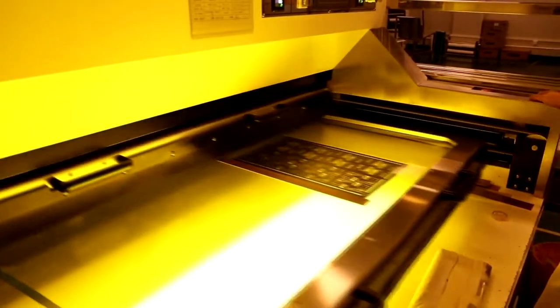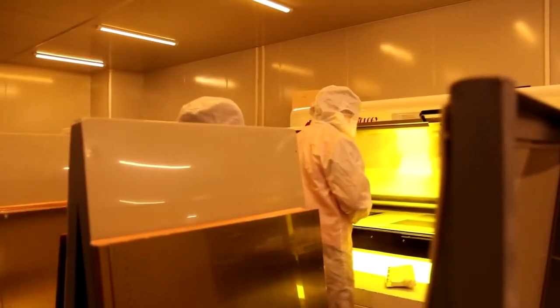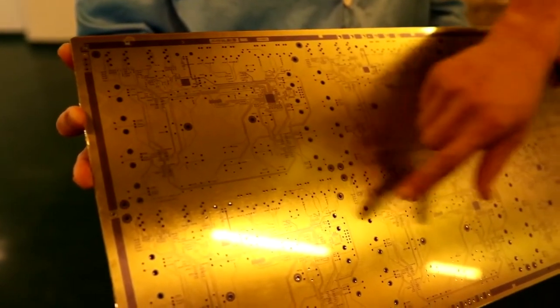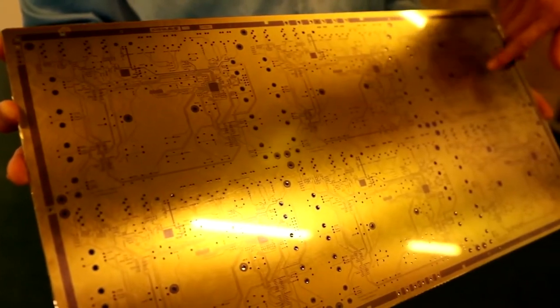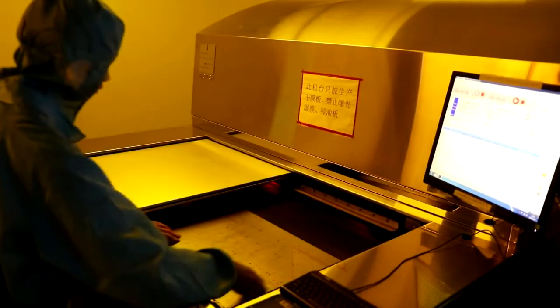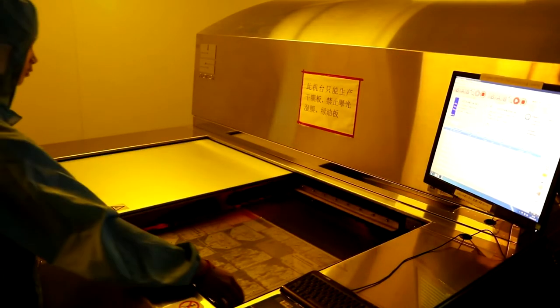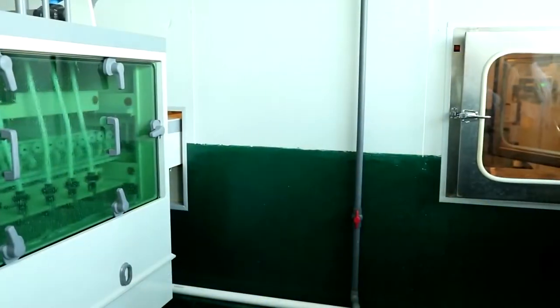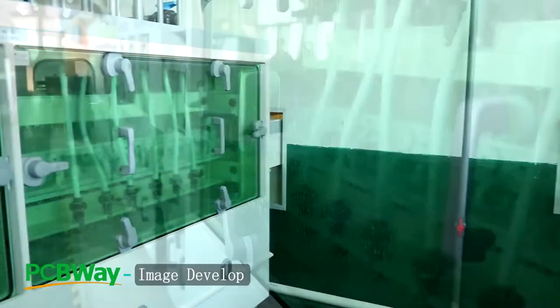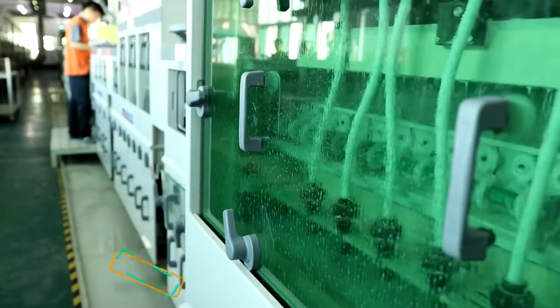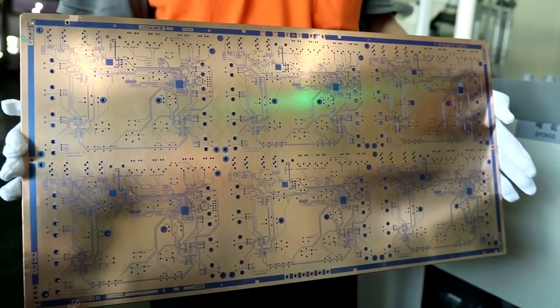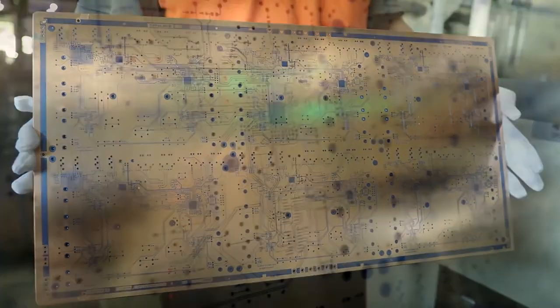Modern machines can do this whole process automatically. Next, the board is processed through a chemical solution, or developer, that removes the unhardened and unwanted resist from areas that were not polymerized by light. After this, you can clearly see only the circuit is printed by blue resist, and this material will resist the chemical at the etching process.